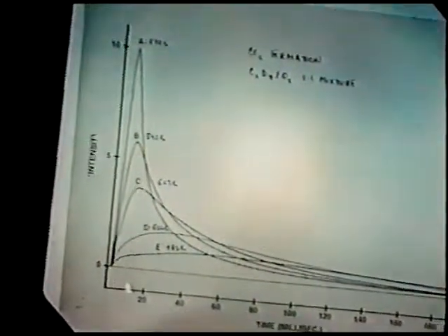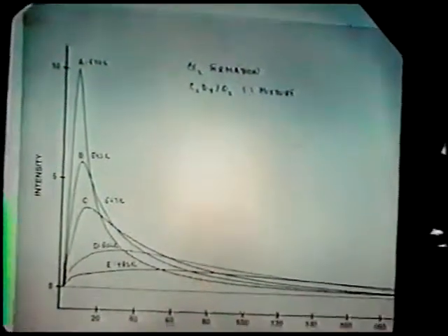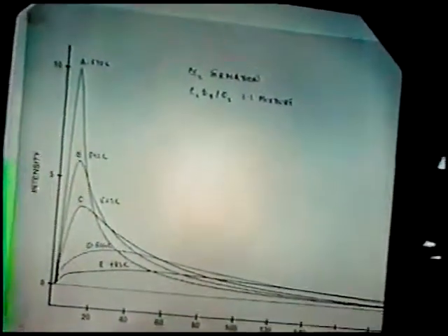As we go to lower and lower temperatures between 570 and 480 Kelvin, the characteristic time for evolution increases dramatically, from just a few milliseconds out to 100 milliseconds. So there's an increase of a factor of approximately 100 in the surface characteristic time for CO2 formation. I'll show you in a moment what we believe this long lifetime is due to, but you see very clearly that the rate of CO2 formation from this reactor is much slower than that for ethylene oxide formation, the shape of which stays almost constant as a function of reactor temperature.